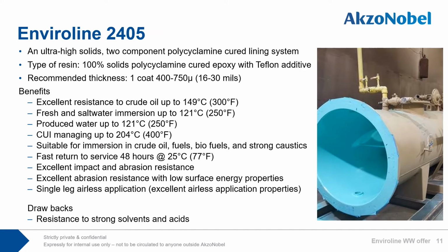Enviroline 2405 is almost as versatile as Enviroline 405 HTR, an ultra-high solids two-component, 100% solids polycyclamine cured epoxy with Teflon additive, applied in a single coat at 400 to 750 microns. Excellent resistance to crude oil up to 149 C, fresh and saltwater immersion to 121 C, produced water to 121 C, can be utilized as a CUI coating, managing up to 204 C, suitable for immersion in crude oil, fuels, biofuels, and strong caustics. Fast return to service in 48 hours at 25 C.